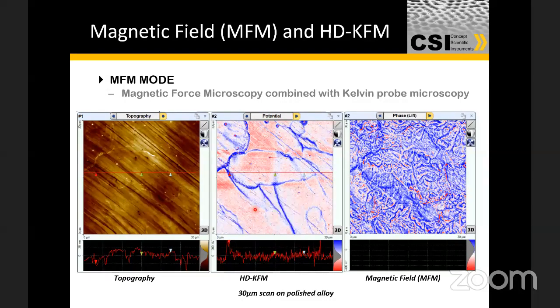Sure. The MFM measurement that we are making is still a dual pass technique, so we're still lifting the cantilever. But because of better lock-in amplifiers these days, we are able to minimize this time. So we can make more real-time measurements even with the lift technique, which allows us almost real time to have the potential, the magnetic and the topography data. However, there is a lift involved in making the magnetic measurements. Do you do the KFM measurement in the lift? No, the KFM is in single pass, but the magnetic measurement only is in double pass. Okay, got it.